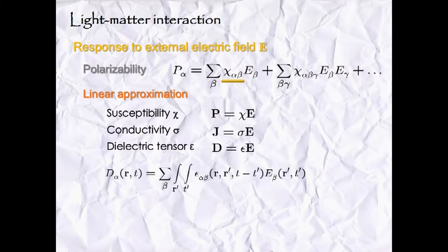So what is the dielectric tensor about? It's quite a pretty complicated object, as you see here. It relates r and r' as a non-local quantity. That means if I disturb my system somewhere at a certain space, I can probe later on at a given time, for instance t' or t, how the system reacts at a different place in the sample. So it's pretty complicated. So say it's non-local in time, it depends also on the time difference, and non-local in space. But it's not typically the quantity that we compute.